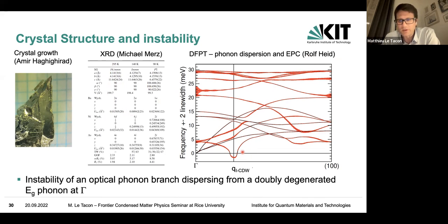And I think in contrast with early calculations on this compound that were maybe not done precisely with the right experimental lattice parameter, and probably also not with the right Z value for the arsenic, maybe with the relaxed value, if you use the actual experimental lattice parameter, what you do find is that this tetragonal structure is actually unstable. So you see a very nice, clear softening of a mode. And if you look carefully, it is softened at finite Q. So in the calculation, the instability is close to a quarter. It's really close to the experimental value.